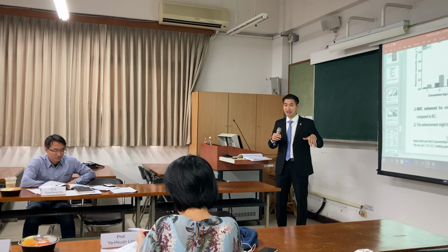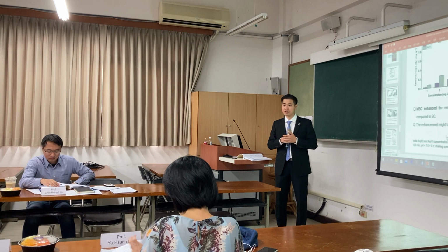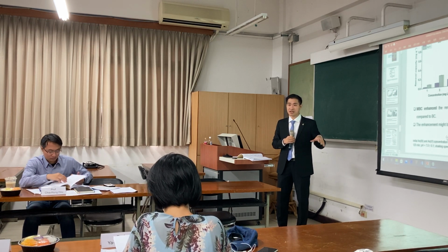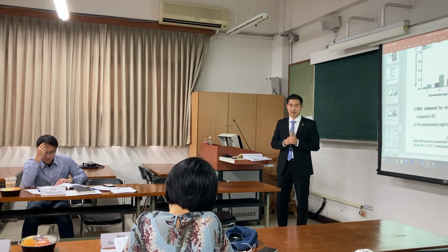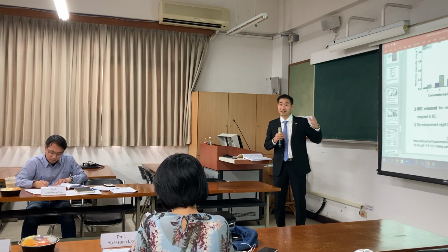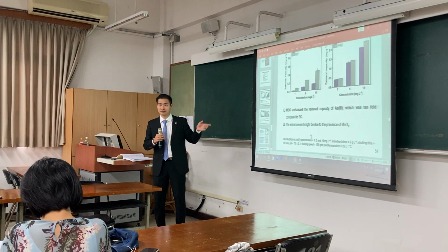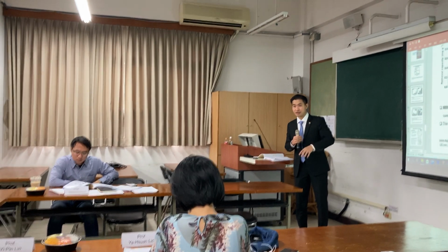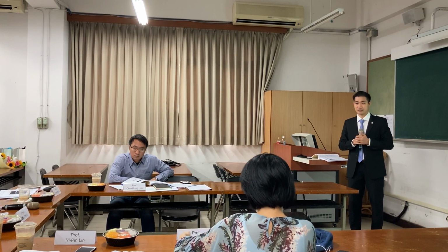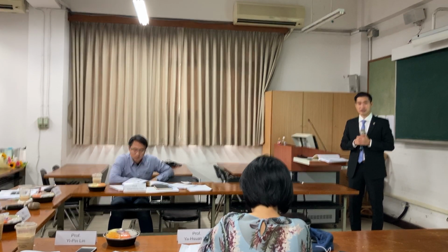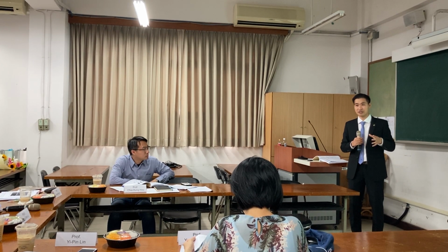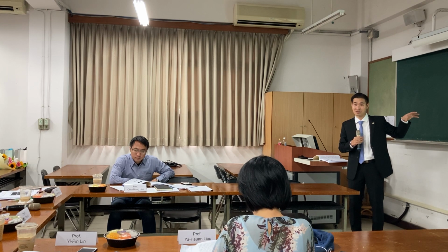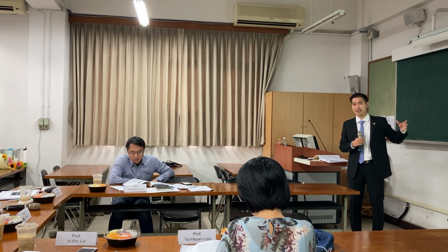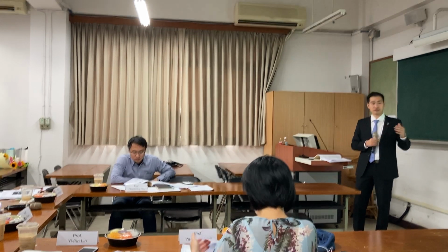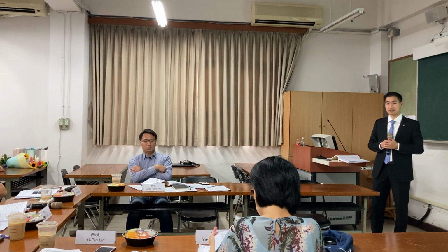The adsorption mechanism explained in my study is surface complexation mechanism. In the beginning, when I started this study, I guessed that maybe after I coated manganese dioxide, because manganese dioxide usually has positive charge at low pH, What is the pKa of the charge for manganese dioxide? I don't remember exactly. It's about 4. Okay, 4. So at pH greater than 4, you have a negative charge surface. Yes. In the beginning I guessed that, but finally I could not achieve this. Maybe due to the mass of manganese dioxide on biochar not being enough, and biochar is very highly negatively charged. Finally, I still achieved high performance for arsenic 3 oxidation and adsorption.